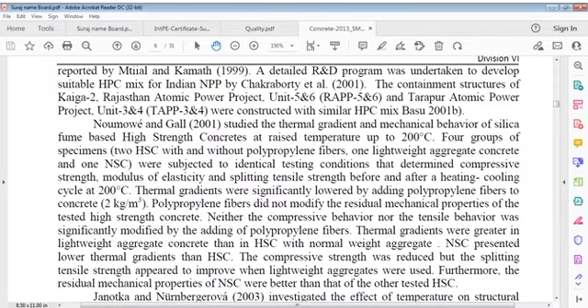It studied the thermal gradient and mechanical behavior of silica fume-based high-strength concrete at raised temperature up to 200 degrees Celsius. Four groups of specimens, two HSC with and without polypropylene fibers, one lightweight aggregate concrete, and one NSC, normal strength concrete, were subjected to identical testing conditions that determined compressive strength, modulus of elasticity, and splitting tensile strength before and after a heating-cooling cycle at 200 degrees Celsius. Thermal gradients were significantly lowered.